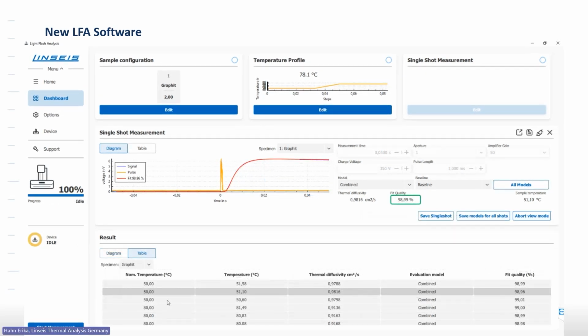So here you can see how this table looks. For the result, we have the nominal temperature, the temperature of the measurement, the recorded thermal diffusivity, the used model, and fit quality. If you have already put in some density and specific heat capacity information, the conductivity would also have been displayed here. A good part is also that if you recognize that one of the shots does not fit the further ones, you can just double click on a line and you can see on the top the recorded curve, where you can find out if maybe something did not work as it should.